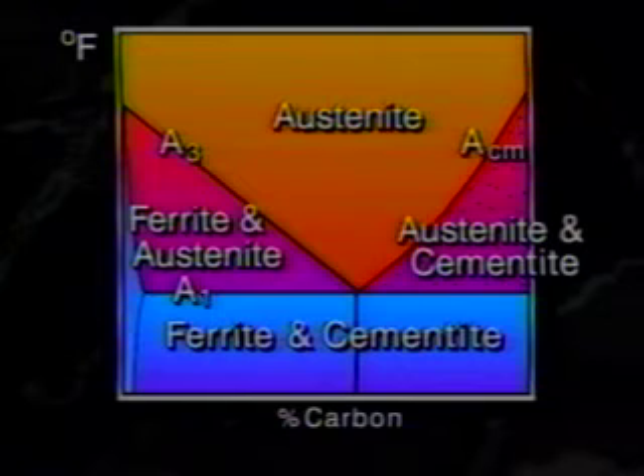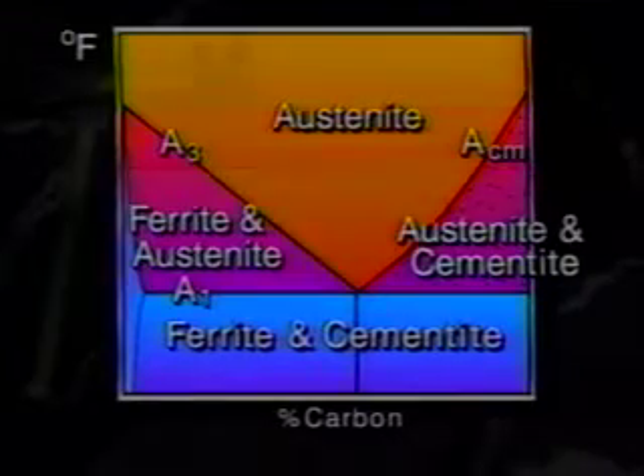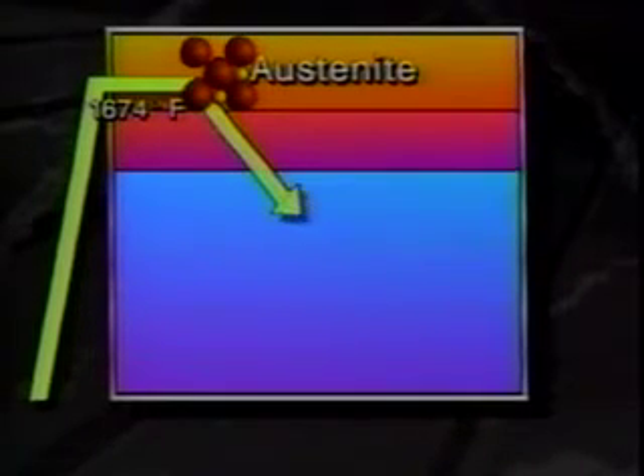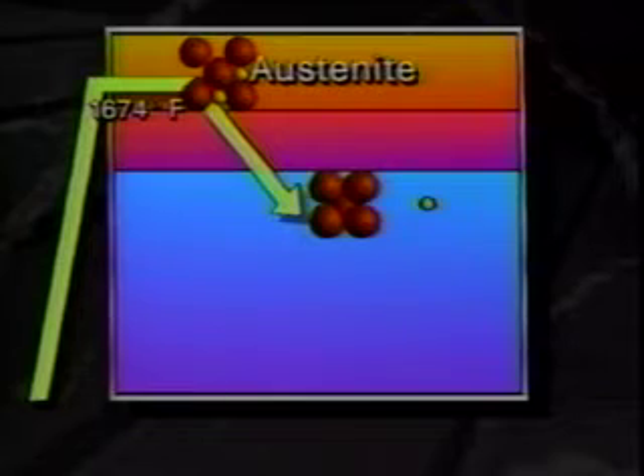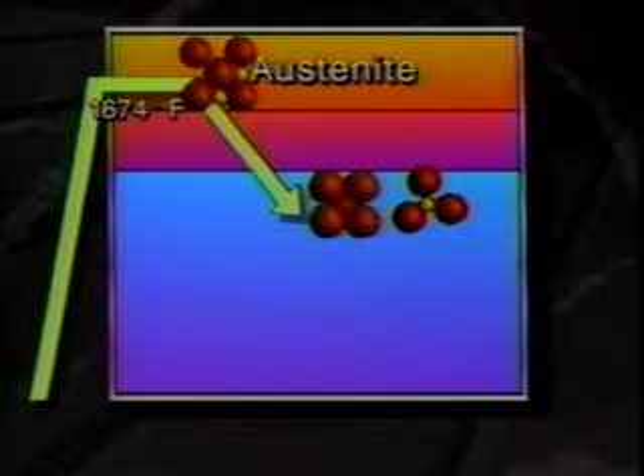When steel is heated to the austenitic temperature range, both ferrite and carbide phases disappear. All the carbon atoms now occupy positions within the crystal lattice of iron atoms. There is only one arrangement of all the atoms, and this is called austenite. If the austenite is cooled slowly, the carbon atoms will not remain in the iron lattice. Instead, they will segregate out as particles of iron carbide.